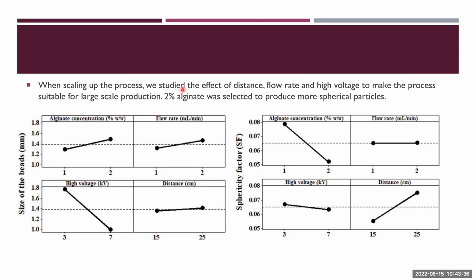So when we scale up the process, we need to find the suitable parameters that make the process reproducible and suitable for this scale up. And many times the process is suitable for lab scale, but when you scale up, it's not suitable because in lab scale, the variability, for example the flow rate or the distance used, is quite fixed. But when you scale it up, there will be a lot of challenges. So we try to find a combination of flow rate and the distance between the nozzle and the surface of the receiving solution that do not have an effect on the bead size. So to make the process reproducible and suitable for scale up, we are looking for the range of flow rate and distance that has no significant effect on the size.